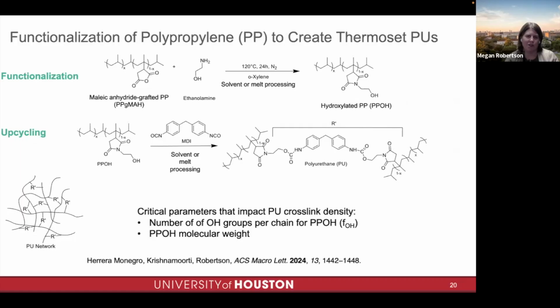So here's the chemistry we'll do. We start with this industrially available maleic anhydride grafted polypropylene. We're going to react it with ethanolamine. Now this can be done either in solvent or under melt conditions, so it can be done in a melt extruder. And we're going to form what we're calling hydroxylated polypropylene, or you'll also see this referred to as PPOH in these slides. Then we're going to take that PPOH and react it with a diisocyanate curing agent. Again, this can be in the presence of solvent or without solvent, and we form the polyurethane network. You're just seeing one strand of the network here, but this is really a 3-dimensional network. Again, the molecular weight that we start with and the level of functionalization will impact the cross-link density of this network.